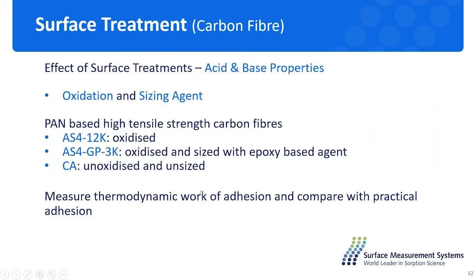And another kind of study for the carbon fiber as well. So we can also study the acid-base property on the surface of this material to study the effect of the treatment. So this time we also have the oxidization procedure added into the carbon fiber. So we have the as-received carbon fiber, the oxidized carbon fiber, and the oxidized and sized carbon fiber. We measure the surface energy of all three carbon fibers, and then we calculate the work of adhesion.